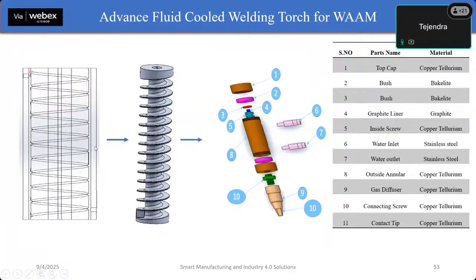This is the basic view of the nozzle. In the center, this is the wire. We have used graphite so that the buckling of the wire can be controlled. After the graphite, the copper tellurium part is there. Between this is the outer annular. This outer annular has also been made with copper tellurium. Between the nozzle and the outer annular, there is some gap. This gap is used to circulate the water into the nozzle. The nozzle design has been made in spiral form to enlarge the surface area, so that the maximum amount of heat conduction can be achieved.